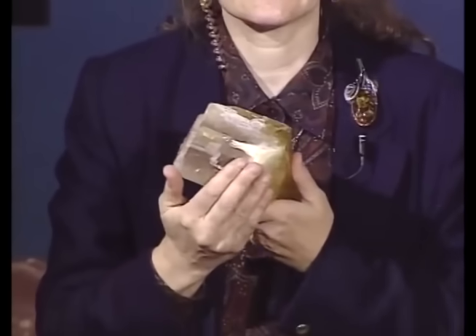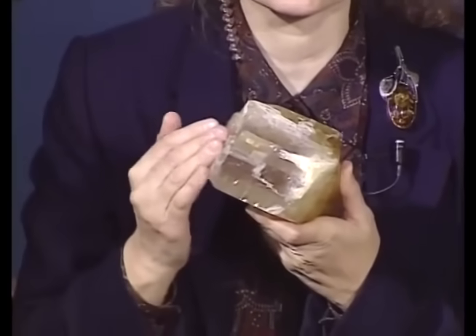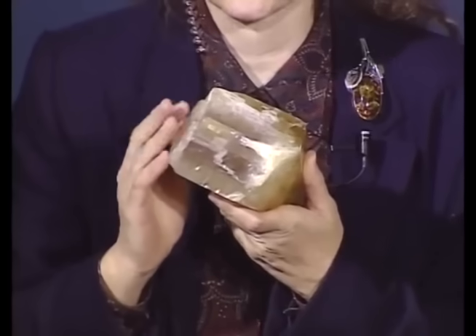Well, the thing about atoms is that they're much, much smaller than the scale that you're smashing this crystal up. In fact, you couldn't really, with a hammer, divide a crystal anywhere near the level of its atomic structure. And because the cleavage, the breaking points of the crystal, as well as the external shape of the crystal, are both controlled by its internal atomic structure, you can never get down to the level where you would be breaking the essential structural element apart in a crystal. And that's why these geometric rules stay true. You can't break through the bricks in the wall. You can only break along the lines of the bricks that have built the wall.